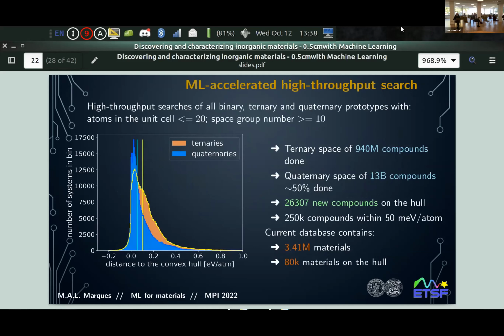We trained the network and we used it to predict stable compounds. We went through a series of prototypes, most of the prototypes that were known for binaries and ternaries. Quaternaries are still not done, but we are going through that also. The space of possible compounds that we scanned was around 1 billion ternaries and 13 billion quaternaries. We just generate these compounds, pass them through the network, and see if the network tells us they are stable or not. In the process, we found 26,000 compounds on the hull. The previous hull, the hull that comes from ICSD, has 20-something thousand compounds, but I will talk about that again. And we found a new 250,000 compounds within 50 milli-electron volts per atom of the hull.